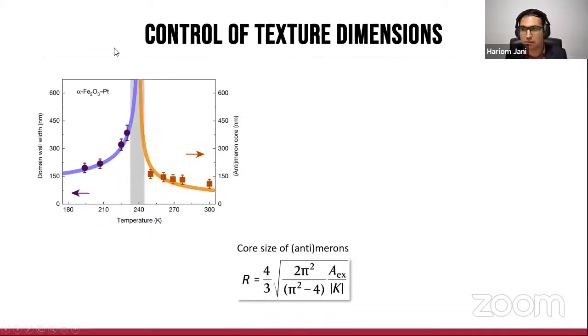We then analyze the evolution of the dimensions of these textures, both the domain wall below the Morin transition, and the gray being the Morin transition, and the high temperature actually hosting the topological objects. And I'm just focusing on the relationship here, which discusses how the full width half maximum radii actually scale as a function of exchange and anisotropy by using a very simple linear ansatz. And we see that the data fits reasonably well.